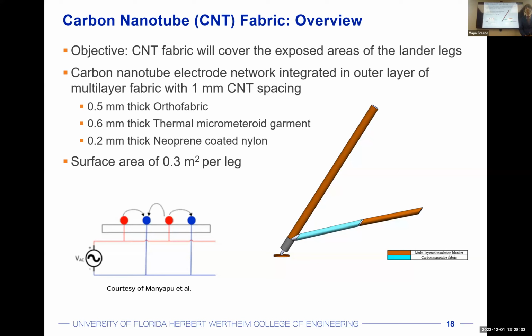The fabric itself consists of an outer layer of ortho fabric, which is 0.5 millimeter thick. This is where the electrodes are actually stitched into. This ortho fabric is a tear-resistant fabric made up of a mix of Kevlar and some other materials. Below that layer is a 0.6 millimeter thick layer of a thermal micrometeoroid garment. This is a mix of 5 alternating layers of aluminum mylar and non-woven Dacron, and then a bottom 0.2 millimeter thick layer of neoprene-coated nylon.